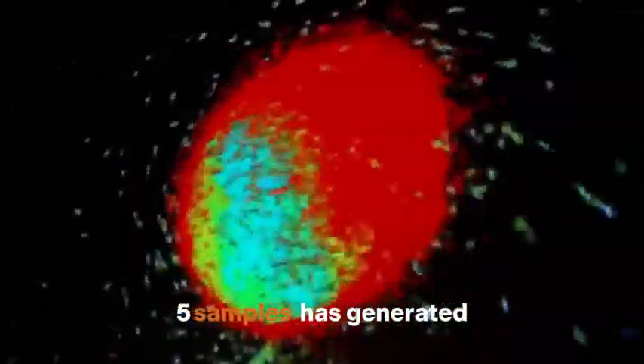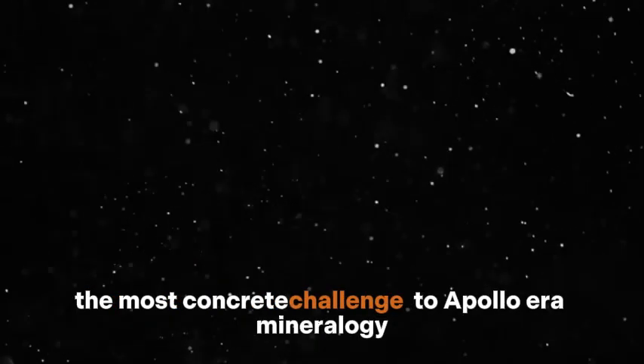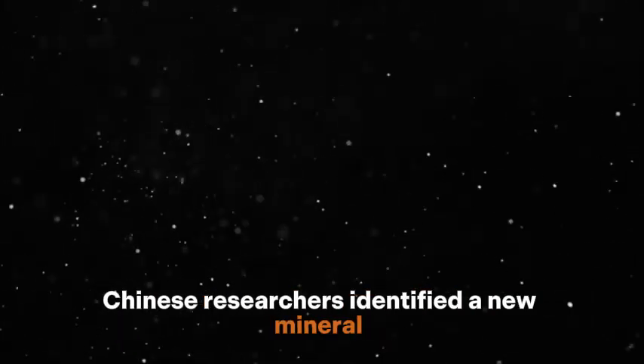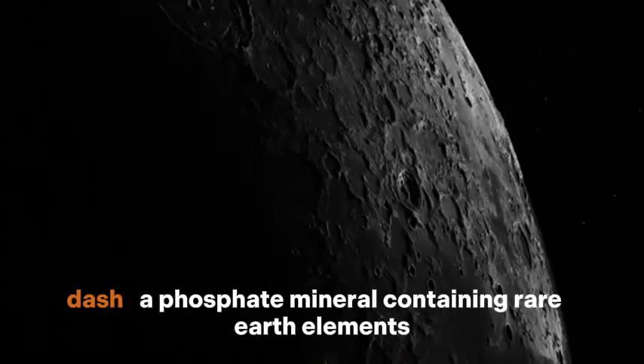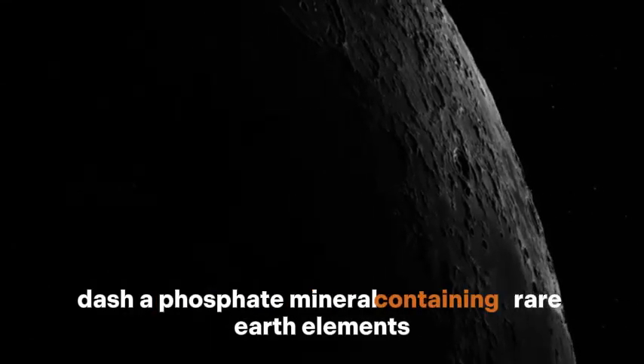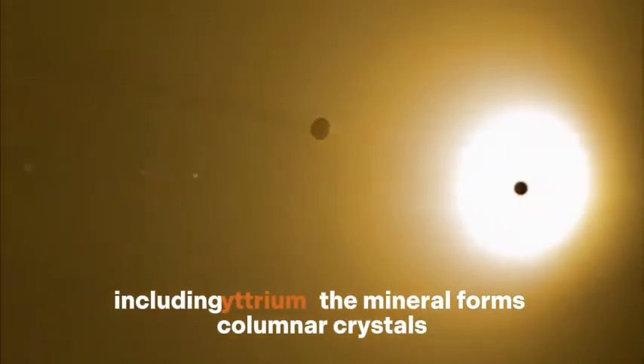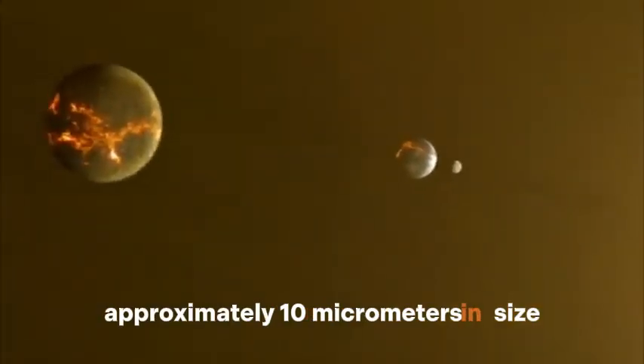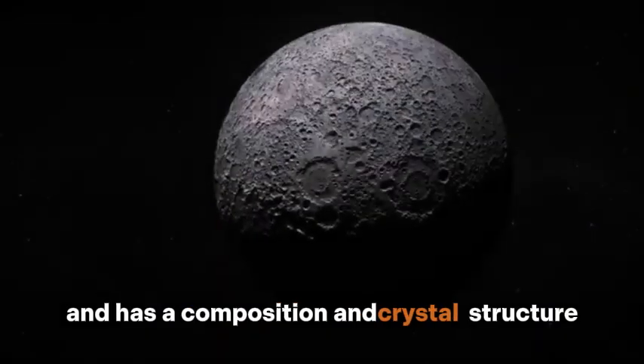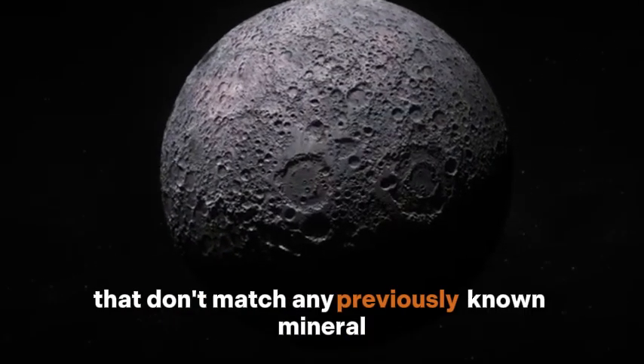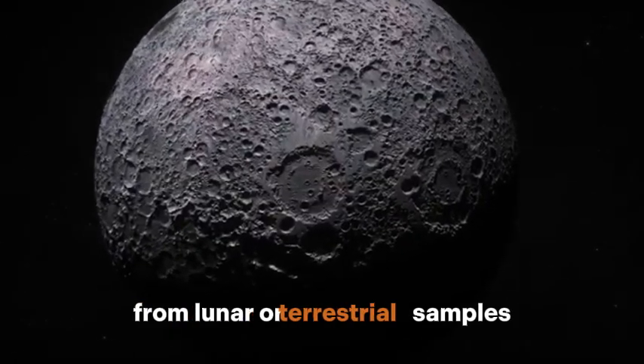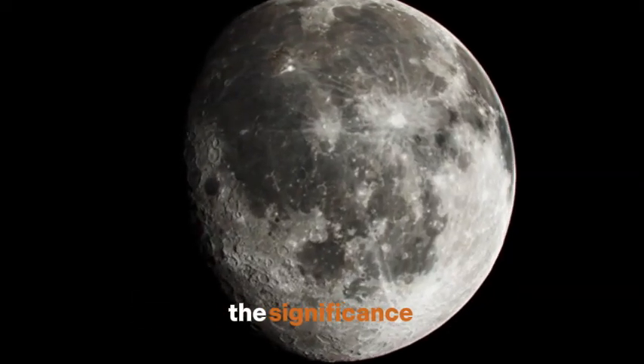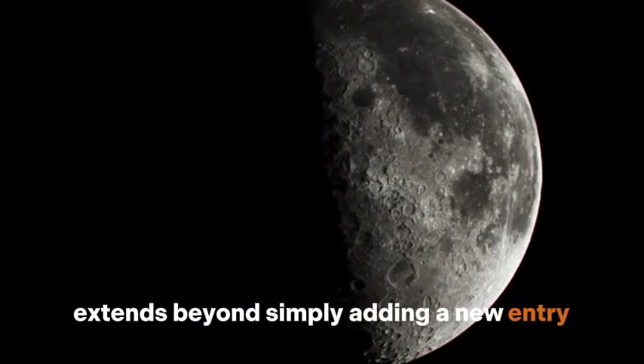The discovery of novel mineral phases in Chang'e 5 samples has generated perhaps the most concrete challenge to Apollo-era mineralogy. Chinese researchers identified a new mineral dubbed Changesite-(Y), a phosphate mineral containing rare earth elements including yttrium. The mineral forms columnar crystals, approximately 10 micrometers in size, and has a composition and crystal structure that don't match any previously known mineral from lunar or terrestrial samples. The significance extends beyond simply adding a new entry to the mineral catalog.